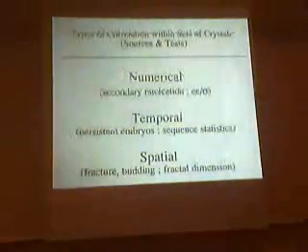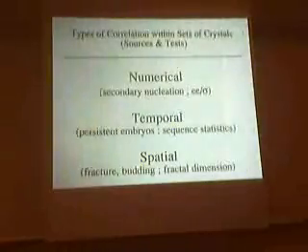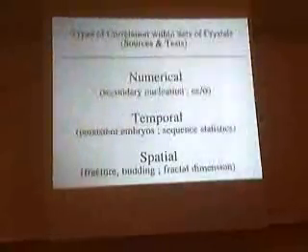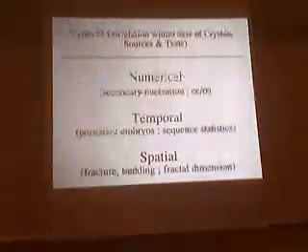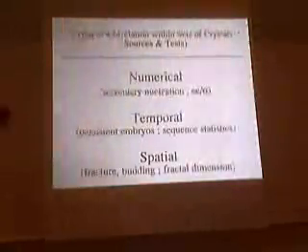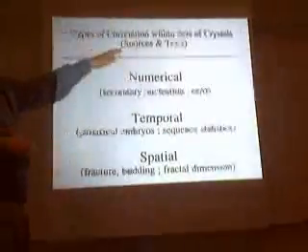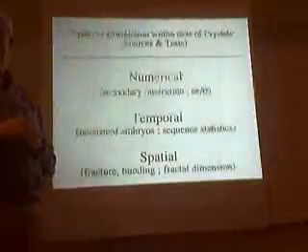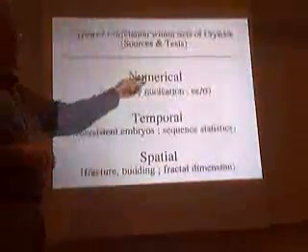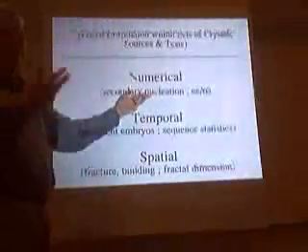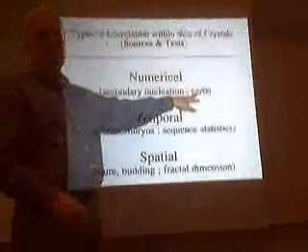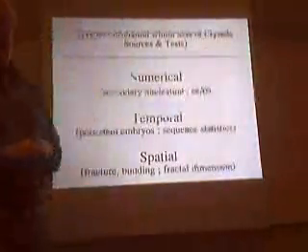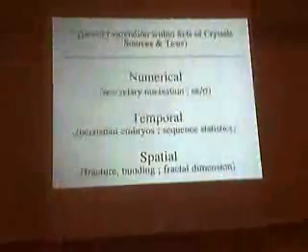Now, getting something homochiral is a question of correlation, getting things to correlate with one another. I made this 17 or 18 years ago, in the context of secondary nucleation. There are different types of correlation within sets of crystals, sources for each type, and tests you can use to see whether it applies. There's simple numerical correlation: if you have secondary nucleation, you tend to get the same hand. You can test it by measuring the enantiomeric excess of crystals, for example in sodium chlorate, but always compare it to what you expect for the standard deviation to see whether it's significant.